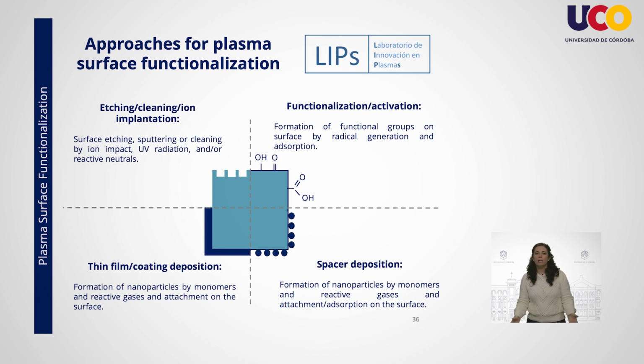In the case of plasma activation, plasma species react with the surface while retaining the original structure of the underlying layers. Both substitution and addition reactions are possible while free radicals are formed on the surface. Surfaces exposed to plasma-active species result in changes in the chemical structure of surface molecules. When active species interact with the workpiece material itself, meaning the substrate, the surface property of the workpiece can change. A new compound can be formed or a molecular fragment can be attached to a polymeric